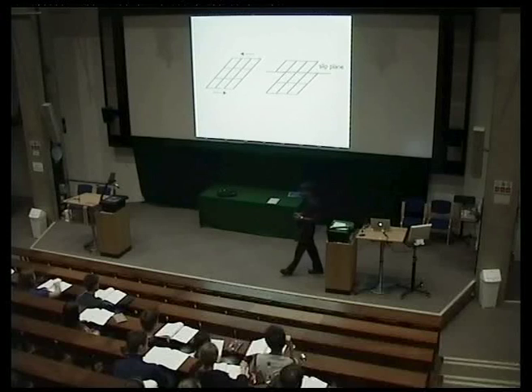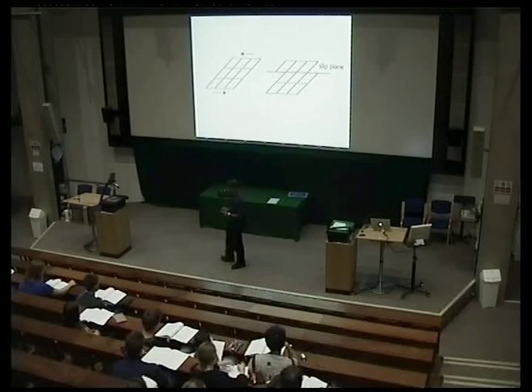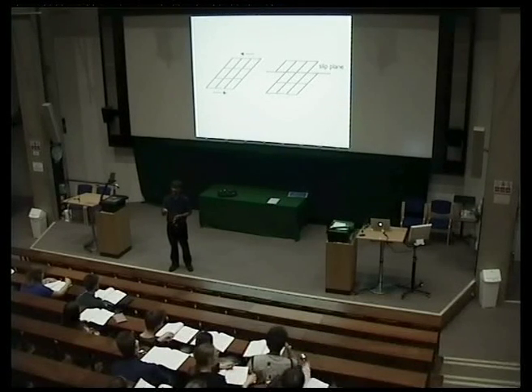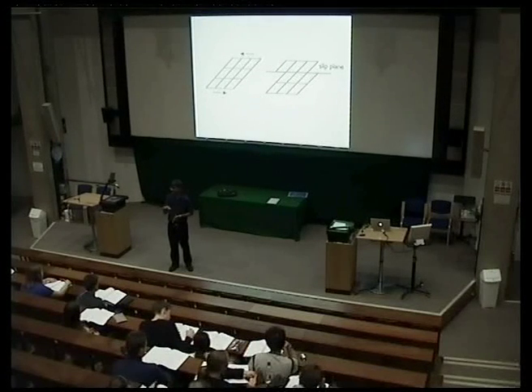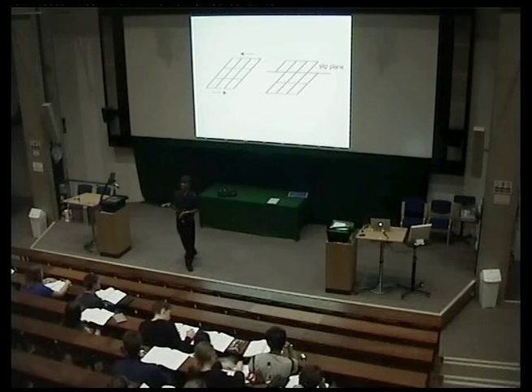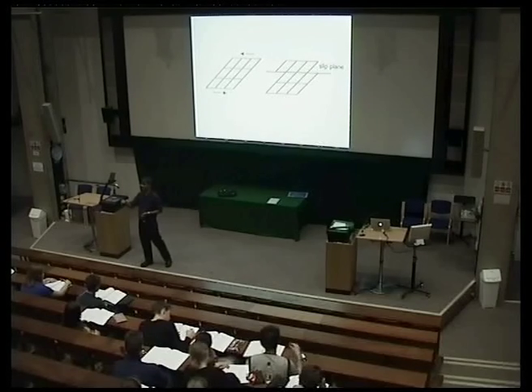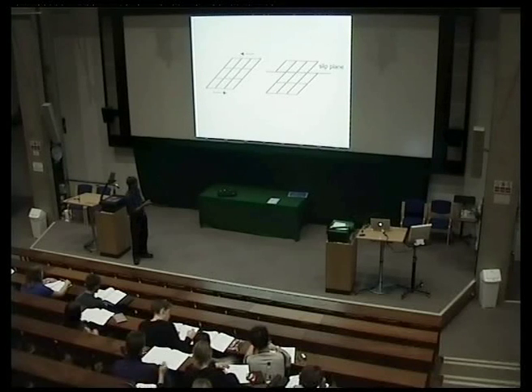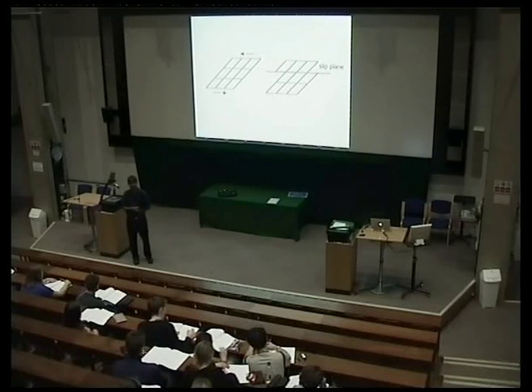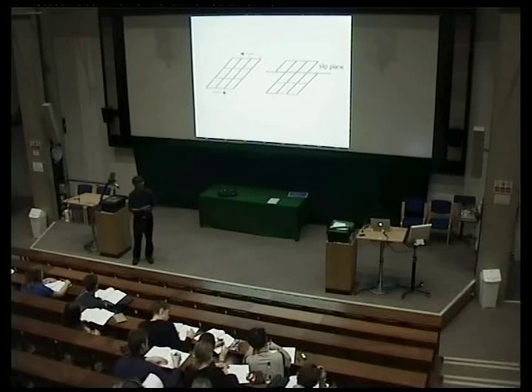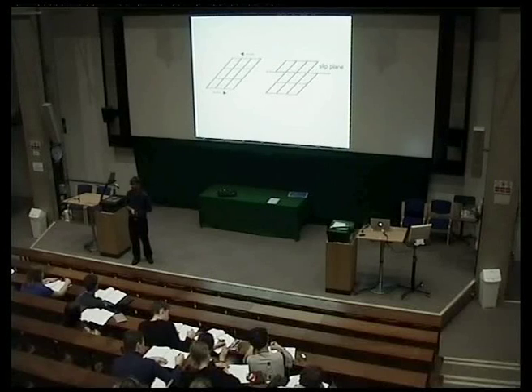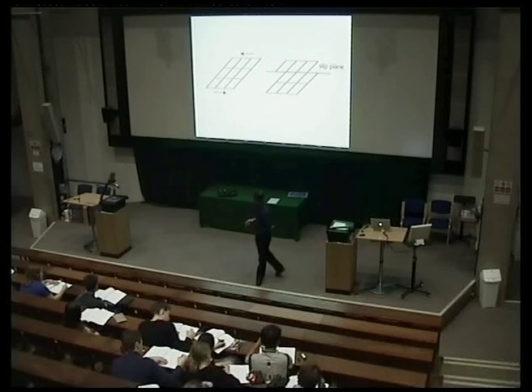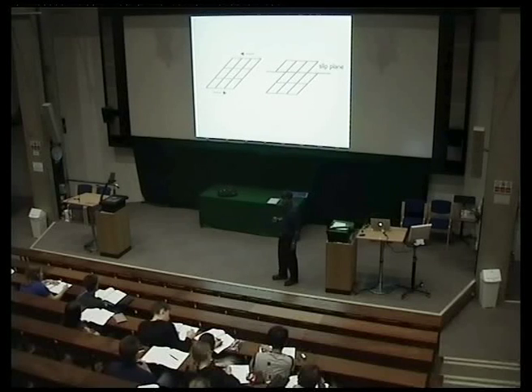You're all familiar with slip deformation, in which we have a crystalline material and we displace it through a distance which is a lattice vector. A lattice vector means you go from one lattice point to another, so you don't see any change in crystal structure when you translate by one lattice point, because the environment at every lattice point is identical. We shear the crystal and displace the top half from the bottom half by a lattice vector — creating a slip step, but absolutely no change in structure or orientation.